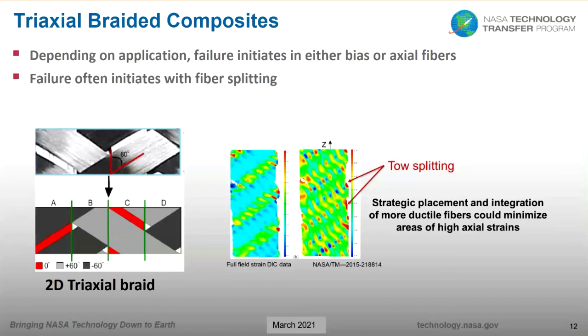On the right, I show a digital image correlation map from a previous study where the red areas in the field strain image are due to tow splitting, but other areas of the triaxial braid, as you can see, were fairly undamaged. So according to this image, it shows that damage such as tow splitting may only be more prone to occur in specific locations of the composite. And if that is the case, then perhaps it is in those specific areas where the more ductile fibers should be placed in order to help minimize the failure.